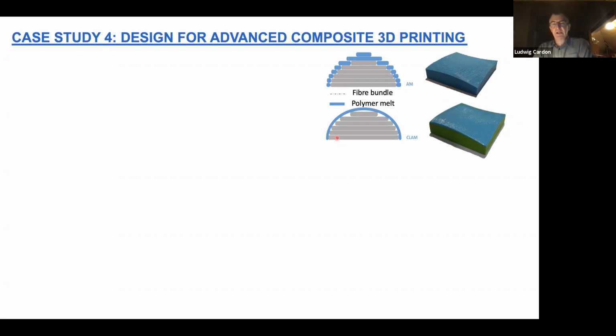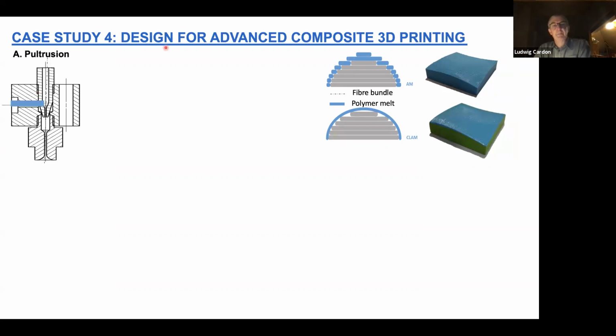So what we developed ourselves is, let's say, the inner printing is like that. And then we do a 5-axis printing, we call it curved layer additive manufacturing, in which we follow the path and we try to optimize the surface roughness or structure of the printing. Besides that, we also combine that with fibers itself. So we developed a pultrusion system. So you pull your glass or carbon fiber through the nozzle, and then the polymer will flow around the material. So we do the wetting, we do the infiltration of the polymer inside the fiber.